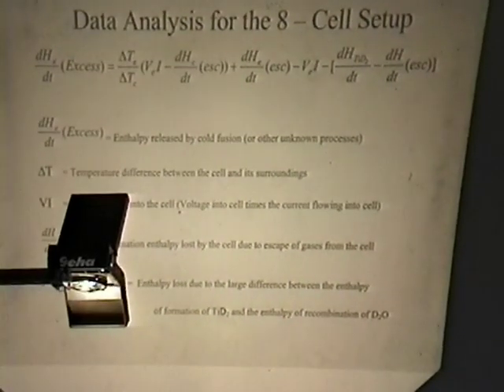Now, to analyze the 8-cell experiment, we've derived this equation here, where this term is the enthalpy released by cold fusion or some other unknown processes. This is the temperature difference between each cell and its surroundings. The subscript here denotes whether it's the experimental or control cells. The VI, that's the power input, voltage and current. This term here is the recombination enthalpy lost by the cell during the experimental run. This term down here is the enthalpy loss due to the large difference between the enthalpy of formation of titanium deuteride and the enthalpy of recombination of D2O. I'm just going through these systems very quickly because we want to get to the results.